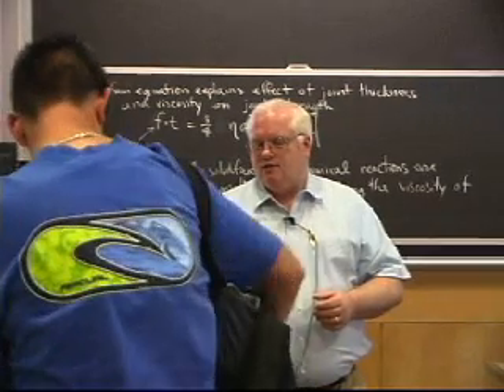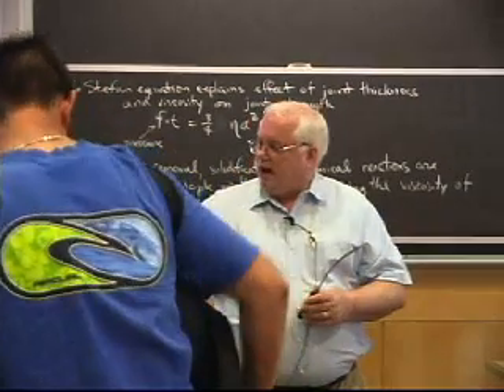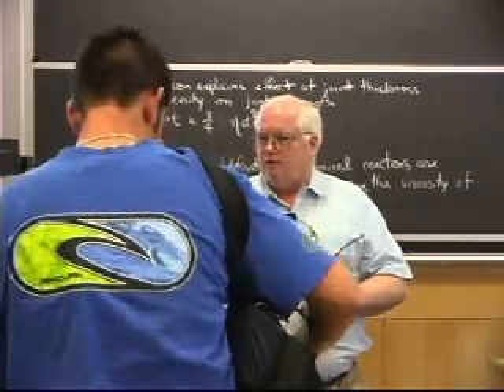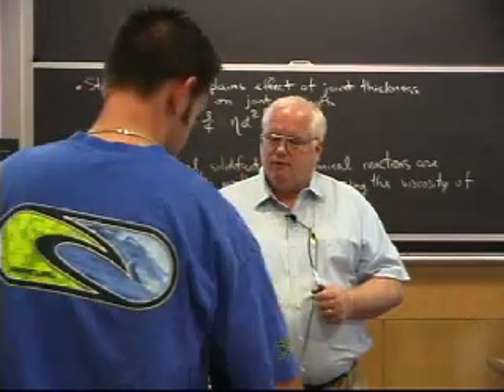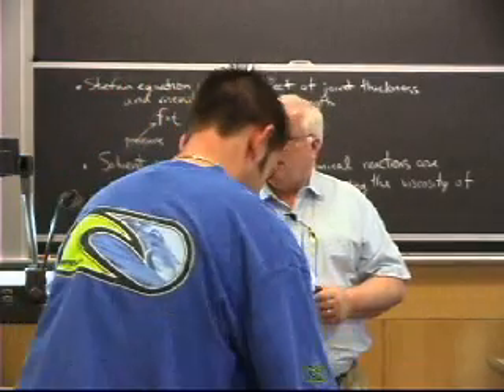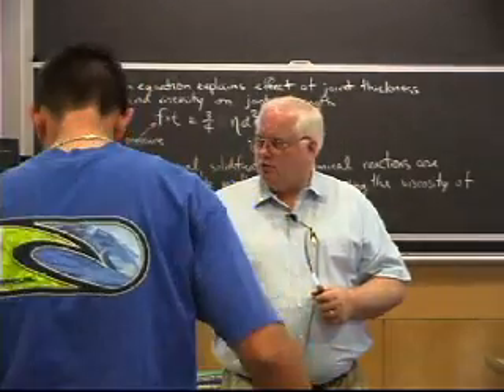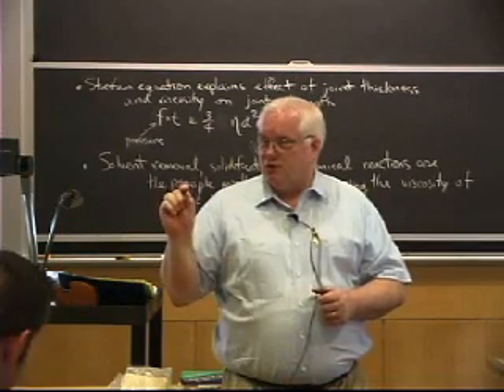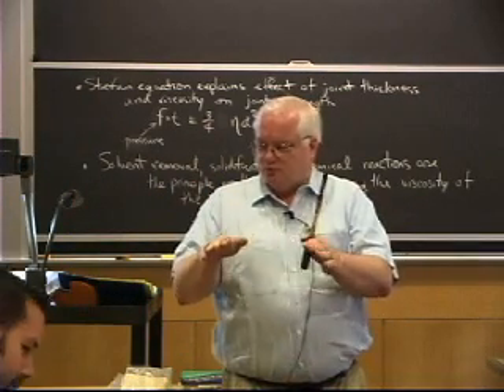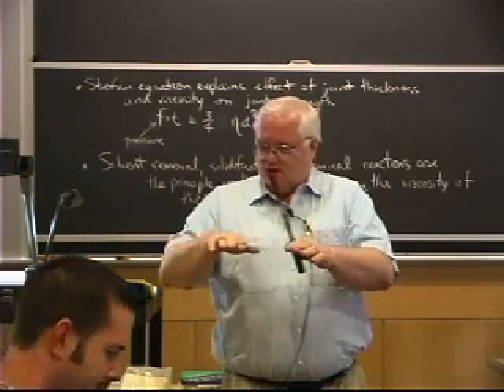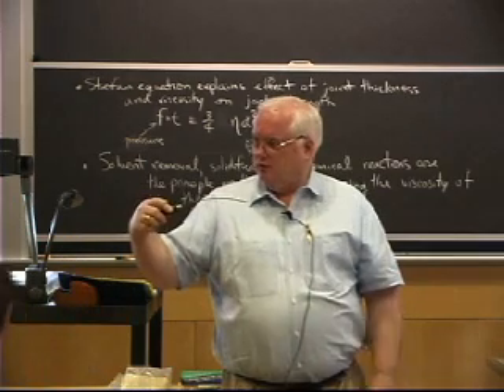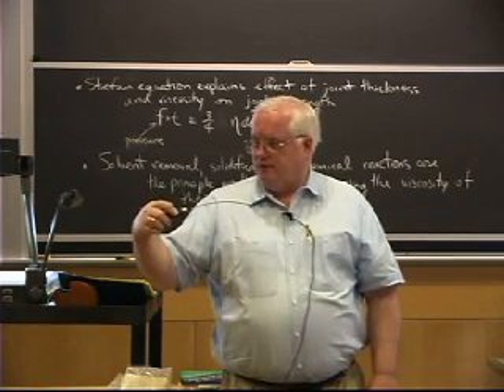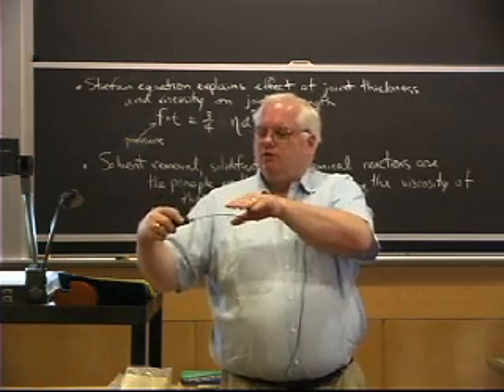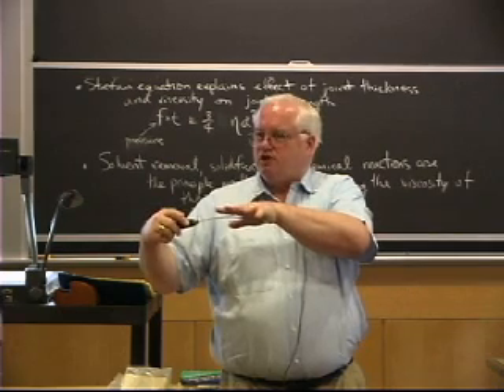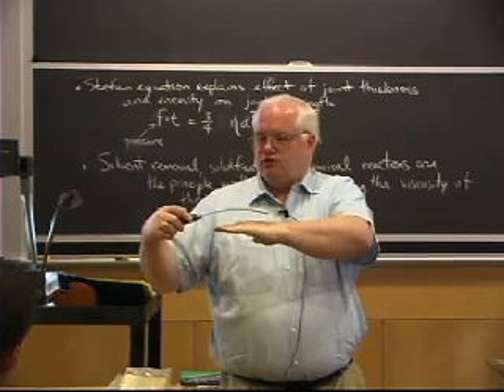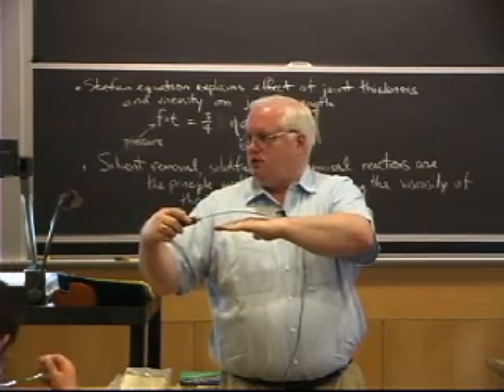In any case, if I had a half-inch thick plate and I took an acetylene torch to it and heated one side for 5 or 10 seconds, the heat won't saturate all the way through a half an inch during that period of time, so the top surface will expand and the plate will bow downward when it's hot. But the material, if I get it warm enough, will start to yield because it's in compression. It's constrained by the material beneath it, which isn't hot.